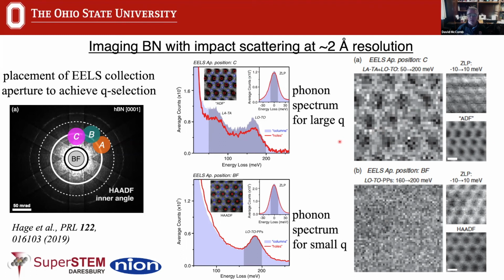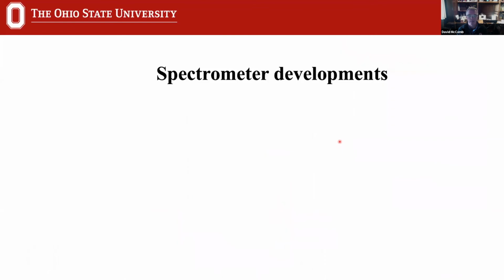Now this is still going to be a challenge because these signals are very weak and require long acquisition times and very stable microscopes, as well as stable energy resolution. But again, a very powerful method. And again, we're trying to explore how we can use this, for example, at CMAS to actually get information around defects in those types of semiconductors that I mentioned earlier. And again, that's a project that Ari Bloomer is taking the lead on.